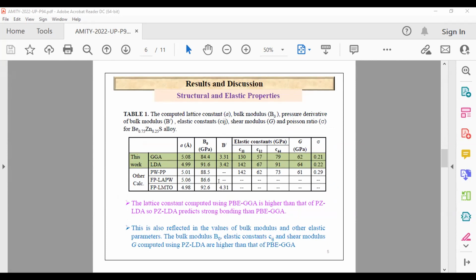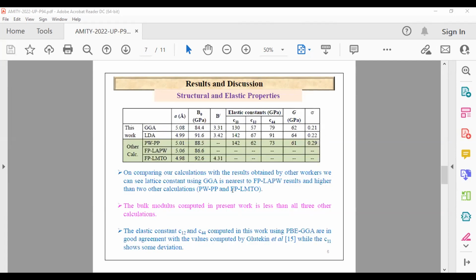This is a hypothetical system, so we cannot find any experimental data for this. So we compared our results with other theoretical calculations performed earlier by other workers using the plane wave pseudopotential method, the full potential linear augmented plane wave method, and the full potential linearized muffin tin orbital method. And we can see that when we compare our results with other calculations, we find our results using GGA close to the FP-LAPW type calculation.